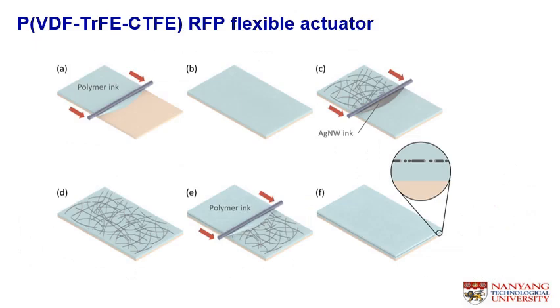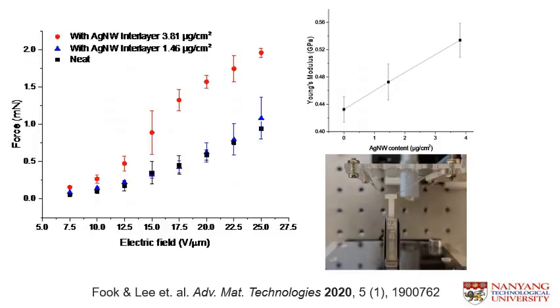The terpolymer relaxor ferroelectric flexible actuator can be improved in performance when we insert an interlayer made of metallic silver nanowire. This can be achieved through a layer-by-layer coating or printing technology. As we can see here, with the introduction of a silver nanowire interlayer into the device structure, embedded within the relaxor ferroelectric polymer, we are able to improve the force output due to the enhanced Young's modulus of the stack. This work shows that the Young's modulus has a crucial impact on the force output.